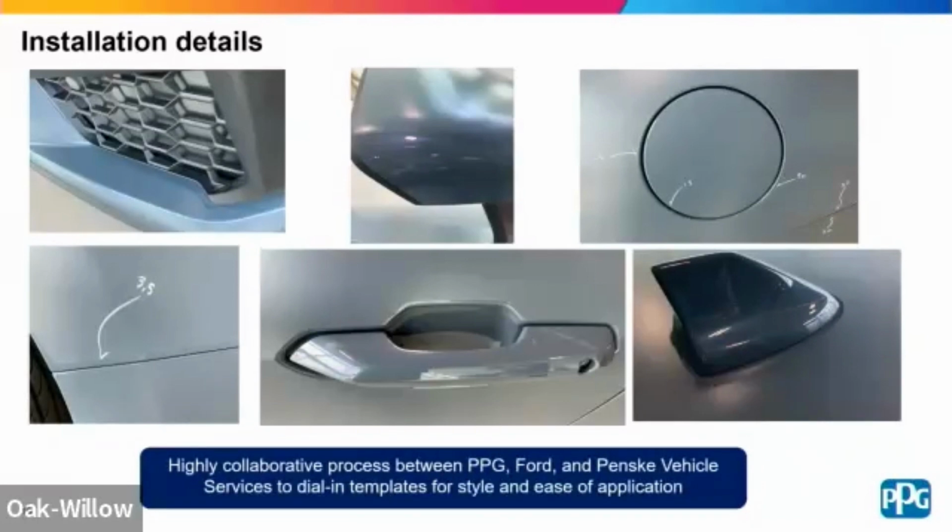And then you squeegee the water out and it sticks down. Okay. But there are a lot of design and engineering considerations when you design those templates. They're designed to within a millimeter, but you have to think about the reliefs. So at the edge of the panel, do you want to show a little bit of the gloss for styling reasons or not? Under the door handles, do you want those glossy or matte? Again, styling. There are some engineering considerations because, as a film, if you stretch it too far, you make it thinner. So you're going to thin that adhesive. So you can't leave too much stress in the film, otherwise it might fail after you put it under durability exposure.